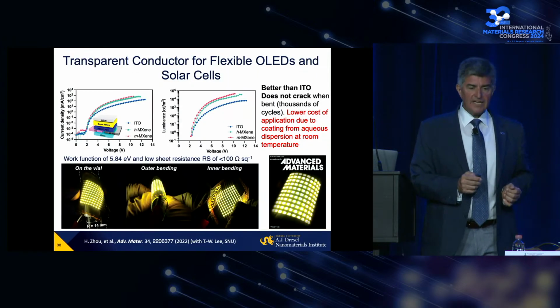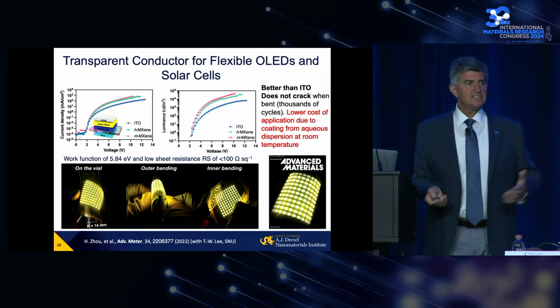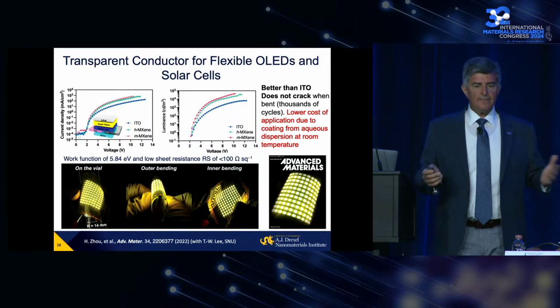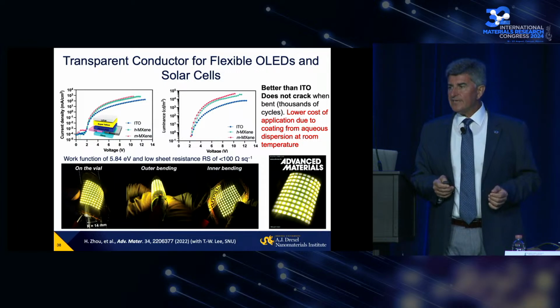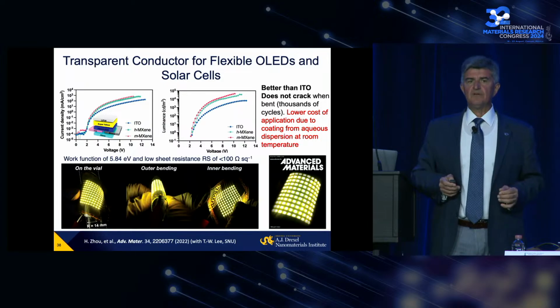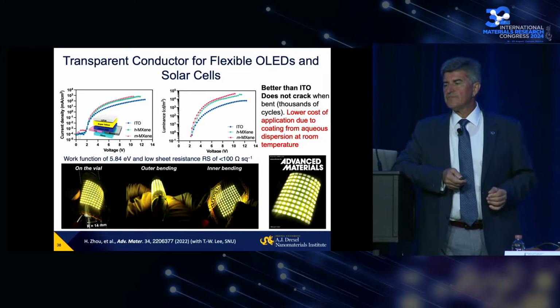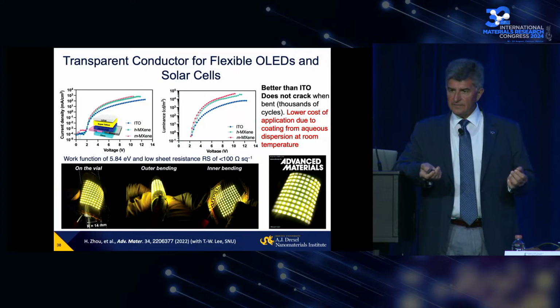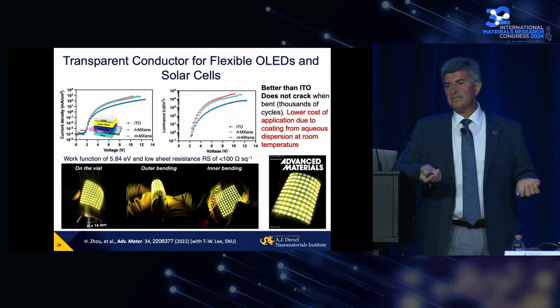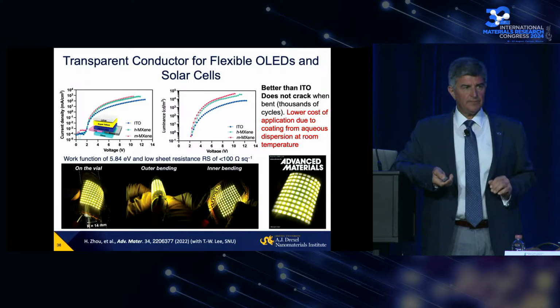This work, again a collaboration with Korean colleagues, replaces the electron transport layer in OLEDs, organic light emitting diodes. And we have been doing very similar work on solar cells, replacing ITO, indium tin oxide, with titanium carbide MXene as a 10 nanometer transparent film.